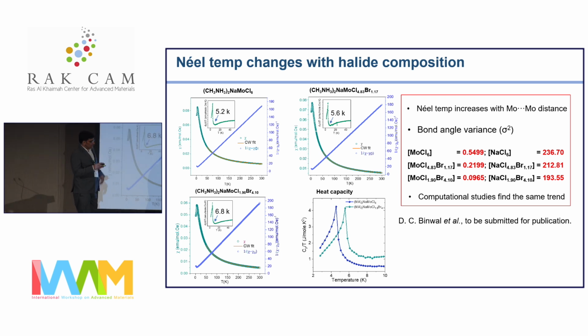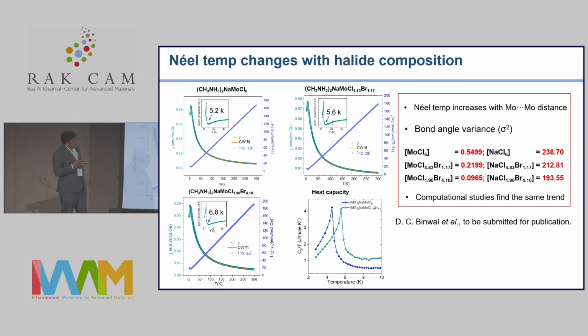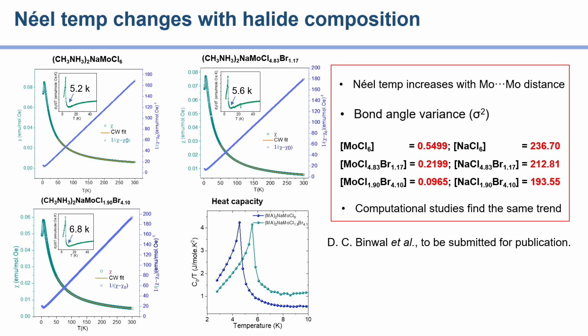Now, what we know so far is, when the molybdenum distance is increased, we see the magnetic correlation strength increasing, but we believe this correlation is due to the distortion in the molybdenum octahedron. So with only chloride, we see the octahedra showing the highest distortion, which is the bond angle variance we calculate using a known formula. And this distortion decreases as you keep on mixing bromide. And probably that is leading to a stronger magnetic exchange interaction. And this was further verified by computational studies in collaboration with Professor Sapanpati's group at JNCASR.